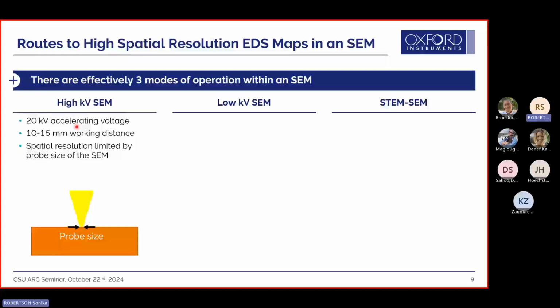So what happens at 20 kV, typical working distance 10 to 15 millimeters, your resolution is limited by the probe size, so you have a larger probe size and you're sampling a lot more volume of the material because your 20 kV electrons, again, are interacting. There's a finite volume down here which limits your resolution in an SEM, even with the latest technology. 30 to 50 nanometer features is what you're capable of resolving with EDS. This is not talking about what you can see in an SEM. This is strictly doing X-ray mapping.